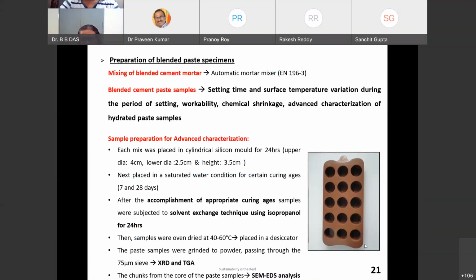So basically we procured this silicon mold, mostly being used for preparing chocolates, mostly homemade chocolates. So we procured this. This is basically a cylindrical silicon mold. The upper diameter is 4 centimeter, the lower is 2.5 centimeter, and the height is 3.5 centimeter. The same conditions were followed, and they were kept for certain durations.